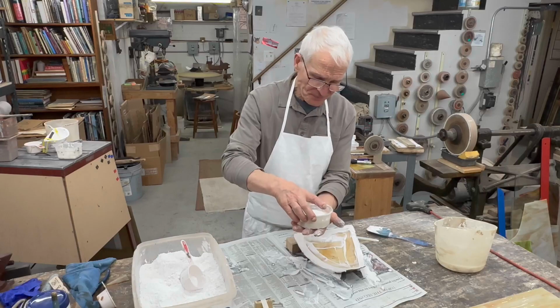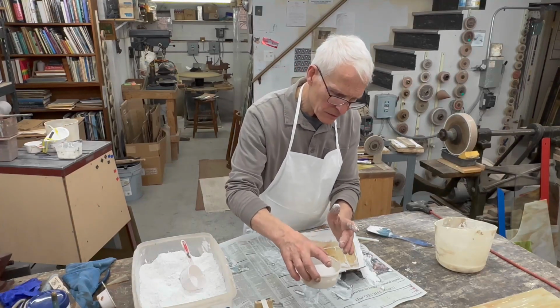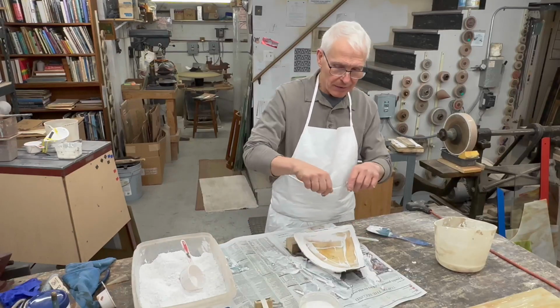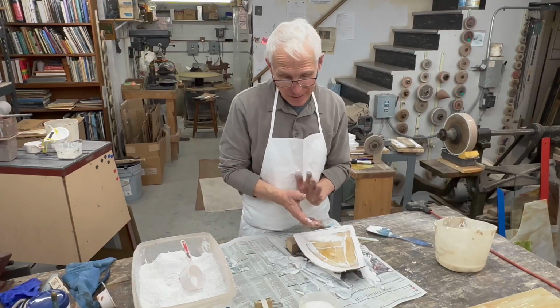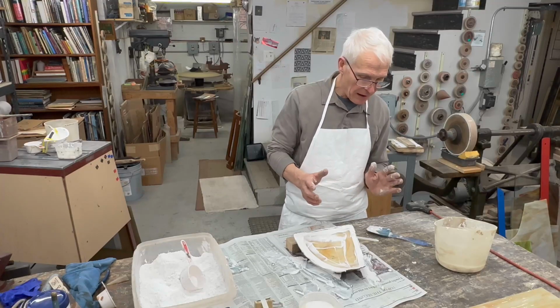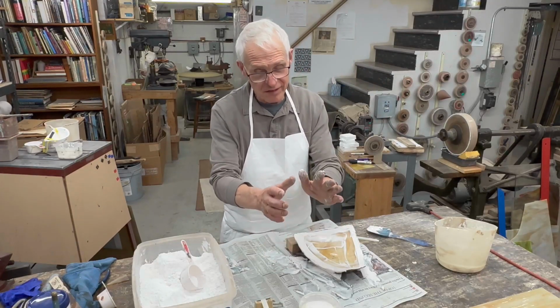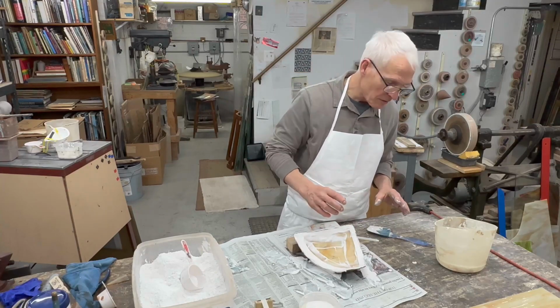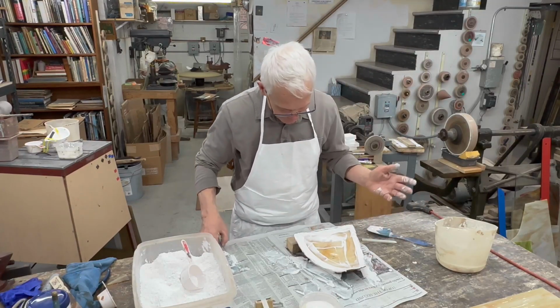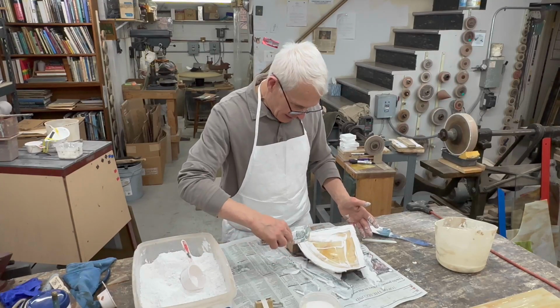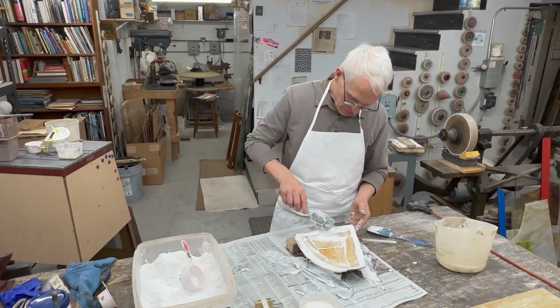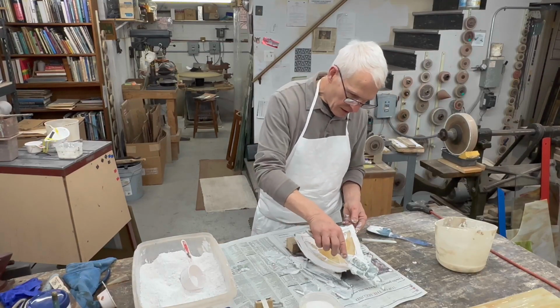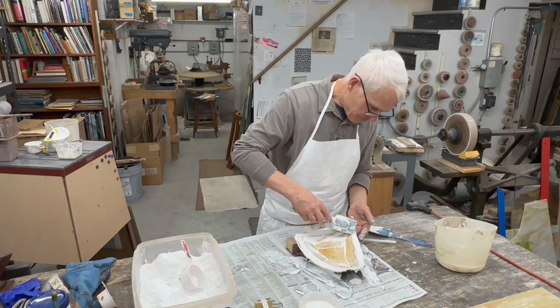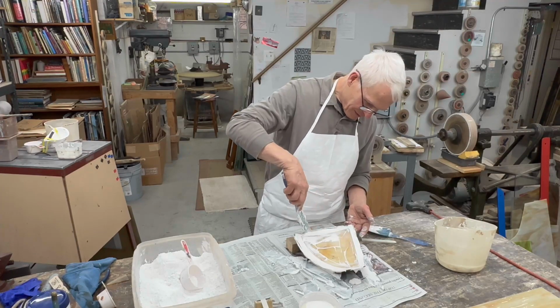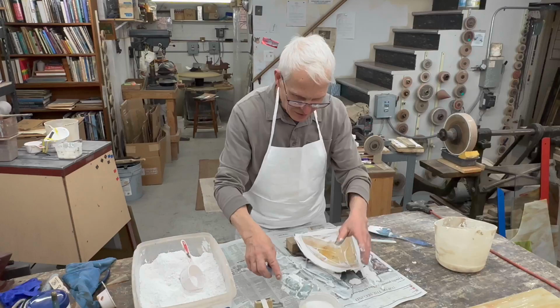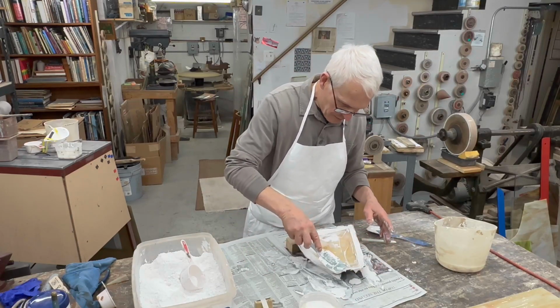You can take a tool while this is still damp but hard and carve anything in there you want, like a rosette or you name it, and then put a flat piece of glass over it and slump it in the kiln, and it'll pick up the texture of that. It's just something to kind of make use of the excess plaster. It's very challenging to try to get the exact amount. It's possible, but more often than not, you either end up with too little or too much.